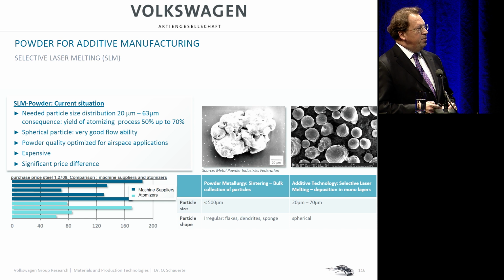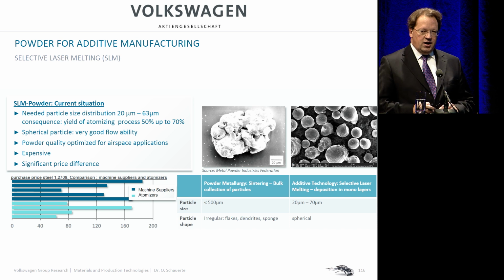This is the typical powder we are facing when we have to make powder components. So you see here it's about 10 microns, the particles about 10 microns thickness. They have to be spherical. They have to have a very homogeneous shape, a size distribution between 20 and 63 micron. And so you already have in the atomizing process a significant material loss.